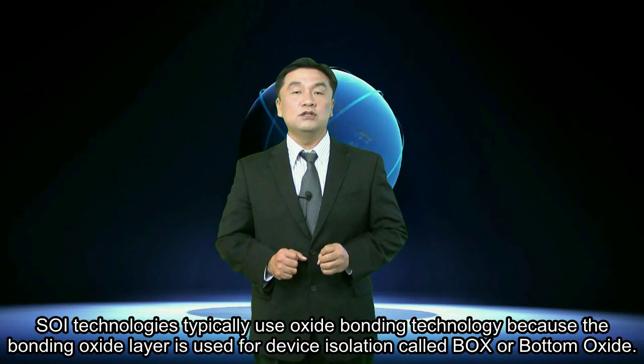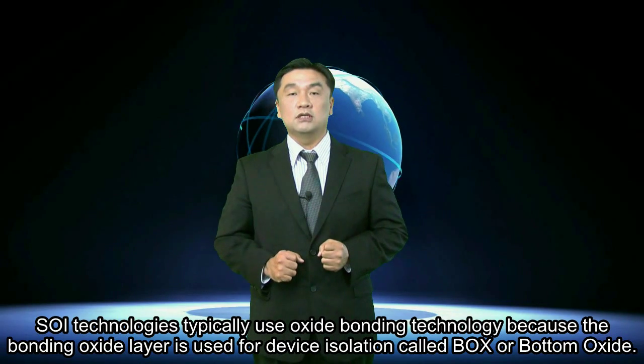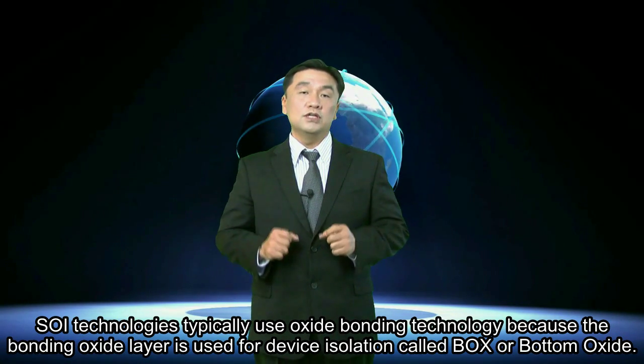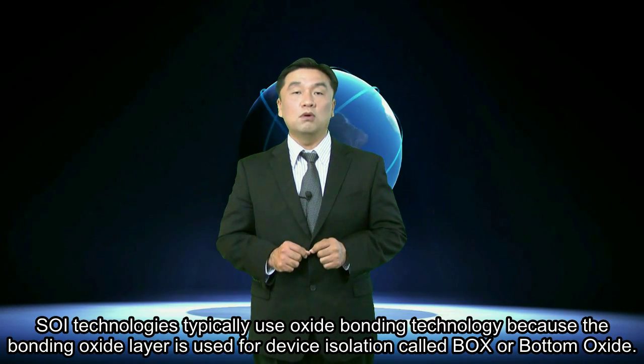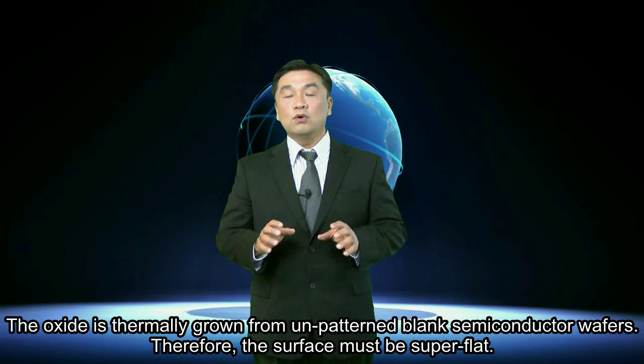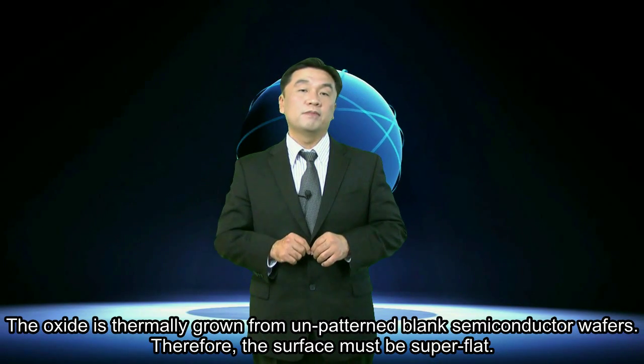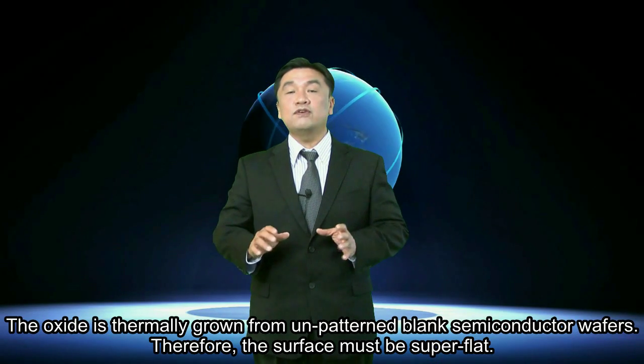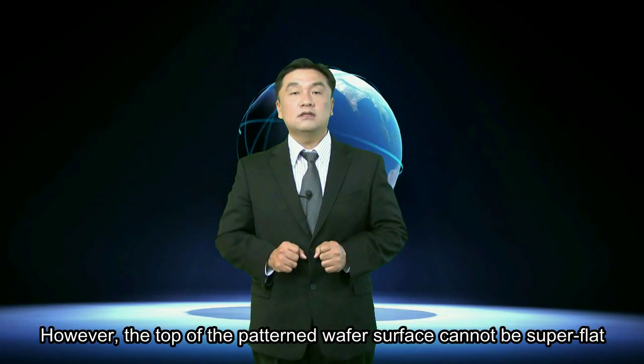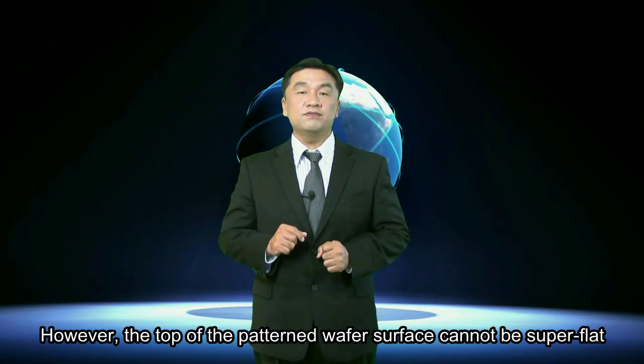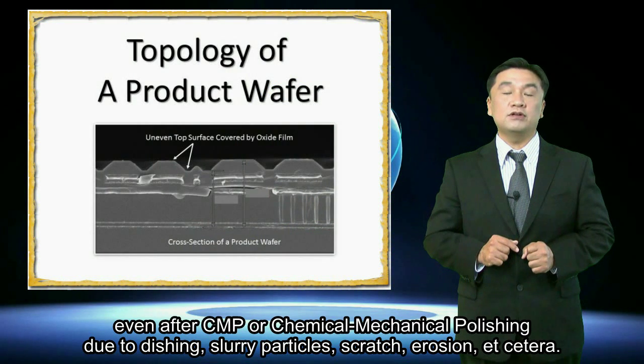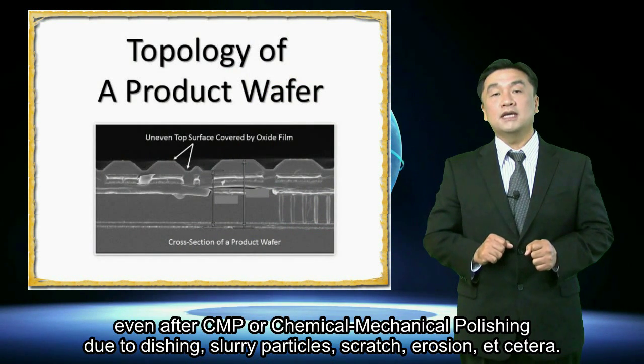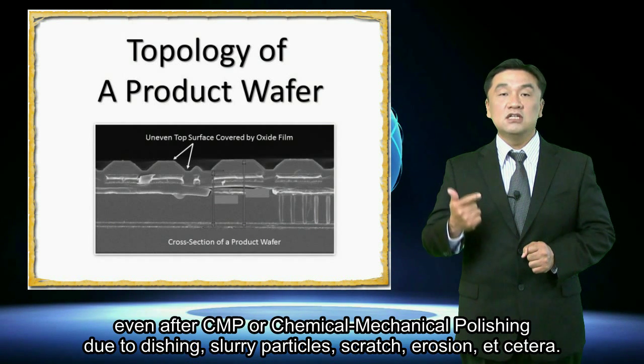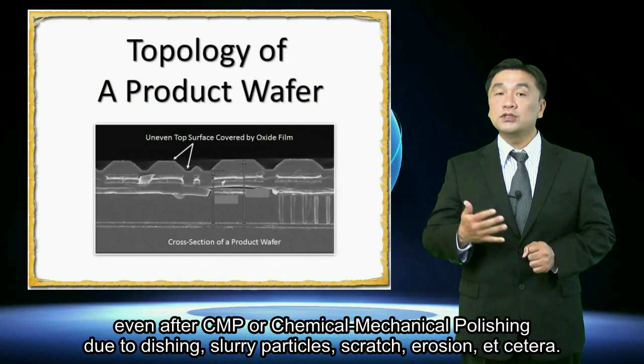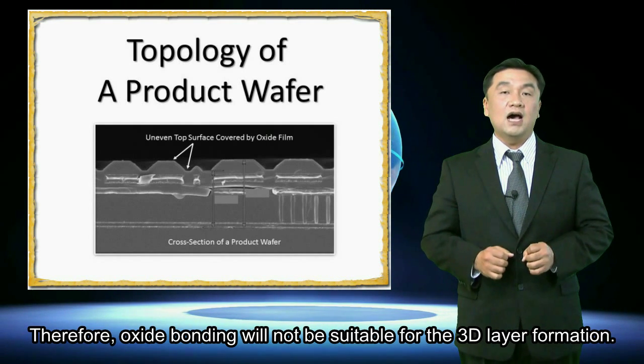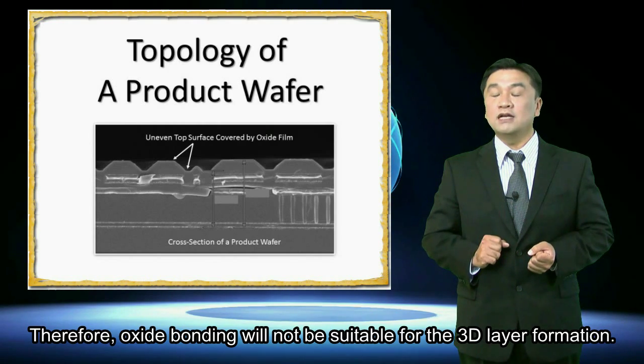SOI technologies typically use oxide bonding technology because the bonding oxide layer is used for device isolation, called BOX or buried oxide. The oxide is thermally grown from unpatterned or blank wafers. Therefore, the surface must be super flat. However, the top of the patterned wafer surface cannot be so super flat even after CMP, or chemical mechanical polishing, due to dishing, slurry, particles, scratches, erosion, etc. Therefore, oxide bonding will not be suitable for the 3D layer formation.